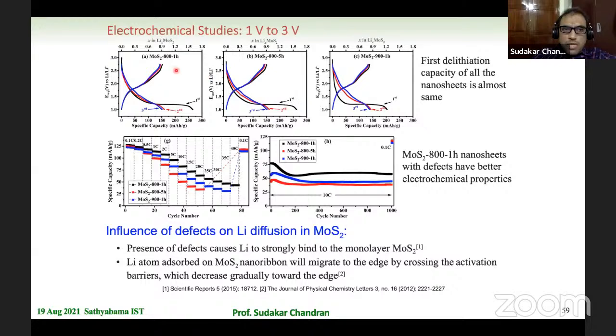And here are the studies we did initially, where 800 degrees for 1 hour, 5 hours, and 900 degrees for 1 hour samples were tested. As you can see, in the very first cycle a large capacity can be seen, 250, 260 milliampere hour per gram for the low temperature annealed one, whereas the high temperature one is much lower. In this particular study, we did the cycling between 1 volt and 3 volt in order not to collapse the nanosheet structure. If you go below 1 volt, your capacity will be high, but then the moly disulfide nanosheet structure will collapse. It would decompose into moly and sulfur, and then it becomes kind of a lithium sulfide battery.